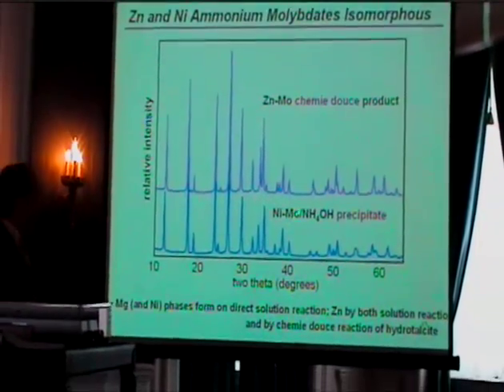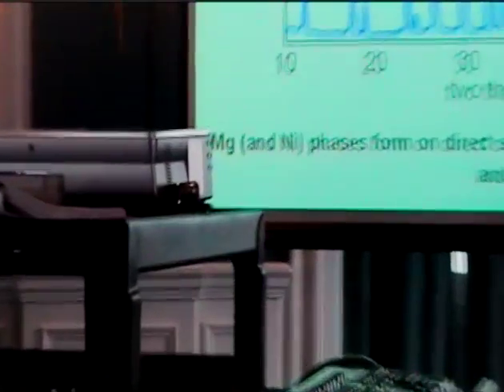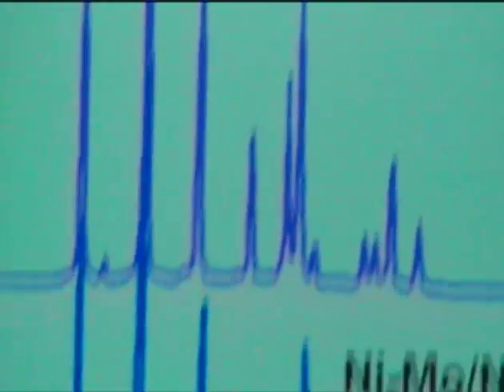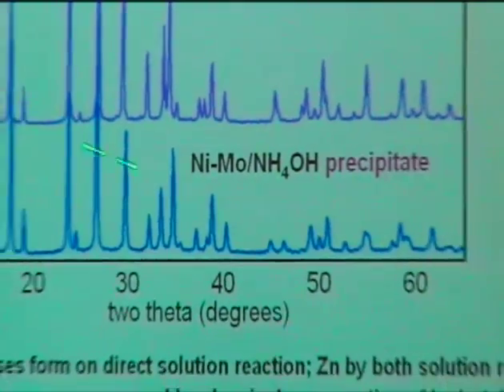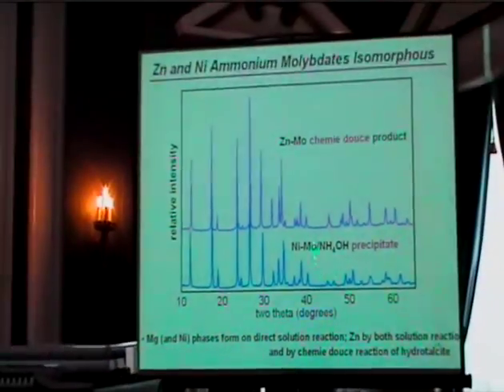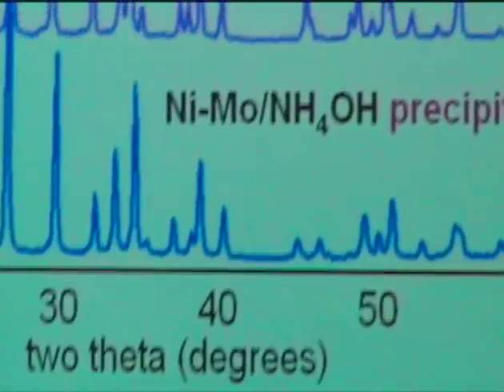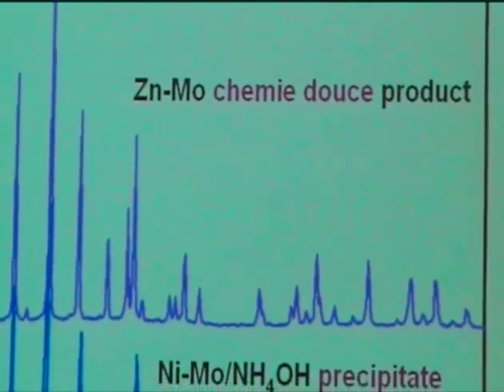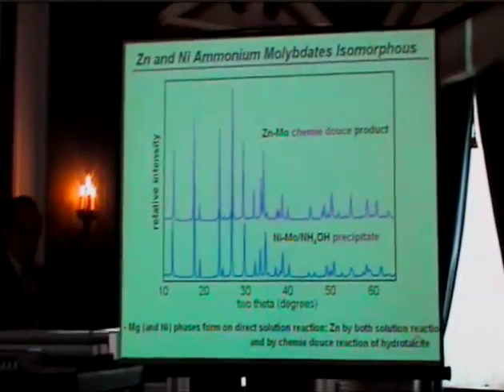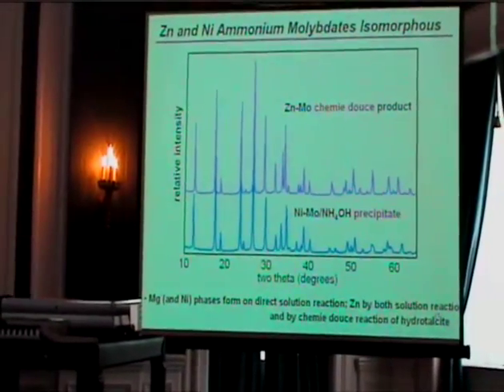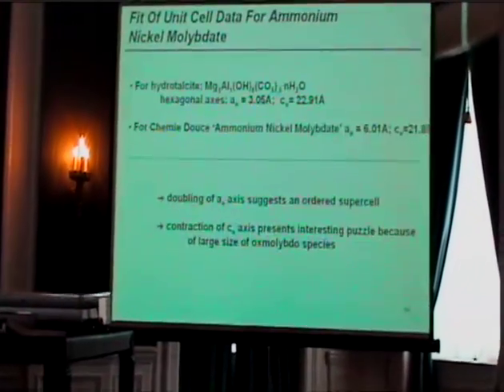So you can see here, for example, this is the chimie douce product that I showed you on the last slide. And this now is if you just take nickel, molybdenum, add some ammonium hydroxide, dissolve everything, boil it up, and drive the ammonia off, you get essentially the same phase. Okay? The zinc you can do by chimie douce, the nickel and the magnesium you have to do by this direct precipitation. There's a reason for that, and I'll talk to you later if you want to hear more about it.